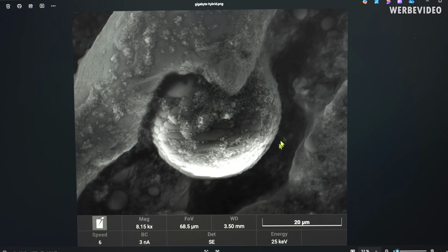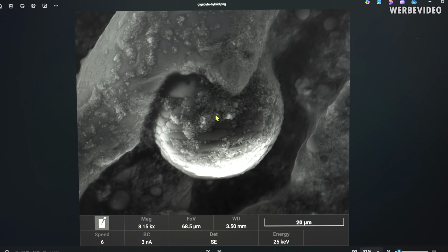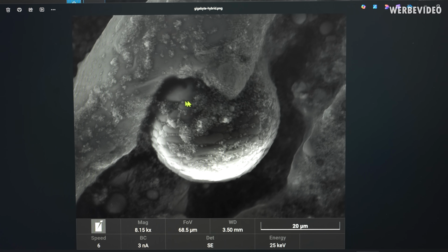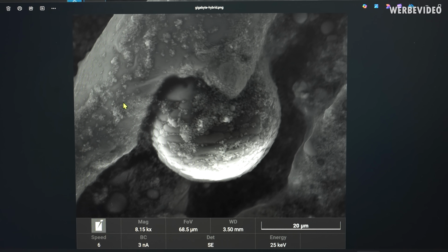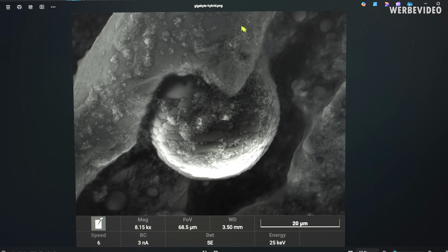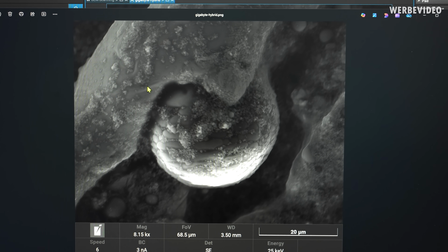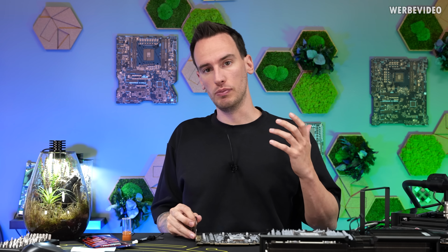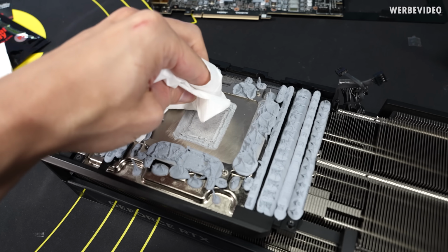Took some time to take a real image. We can see this round shape, that's the aluminium oxide we just looked at with all those tiny particles on top, that's zinc oxide. And then what's sitting all on top right here, that is the liquid metal. Now that things are confirmed, we know it's a hybrid liquid metal paste, we can wipe it off, remove it, clean it, and then freshly apply normal liquid metal.